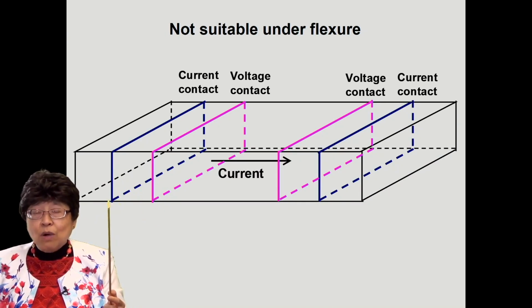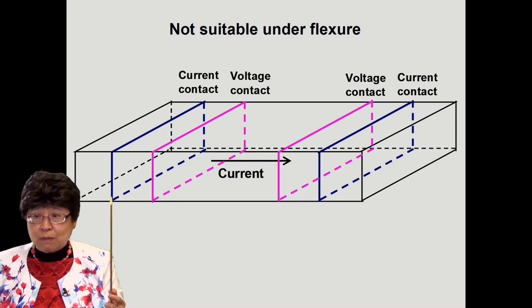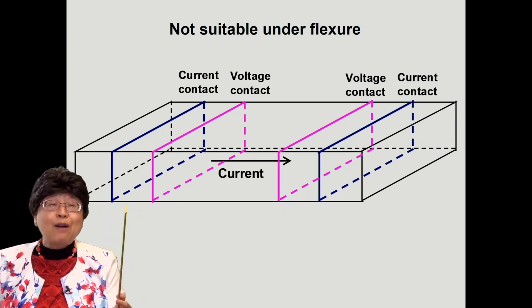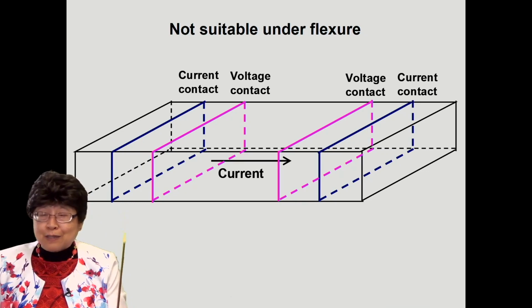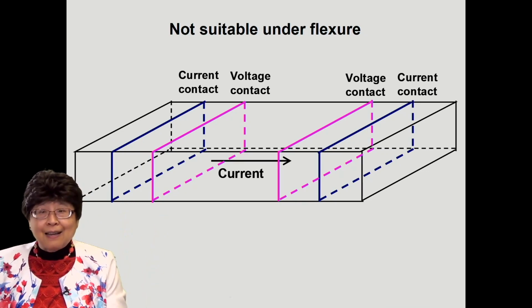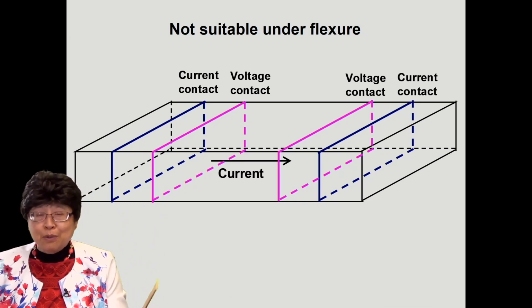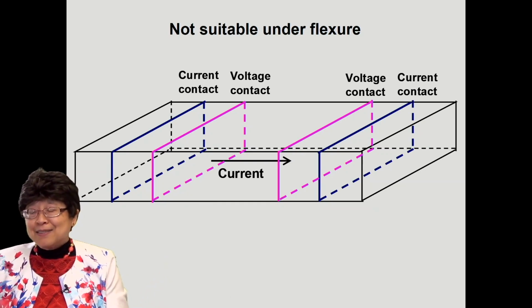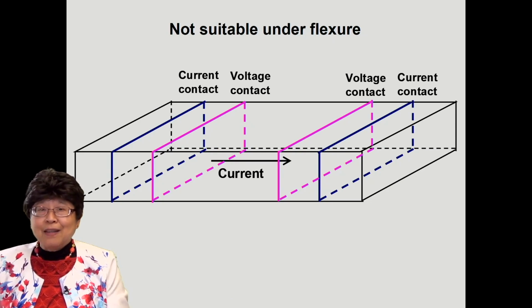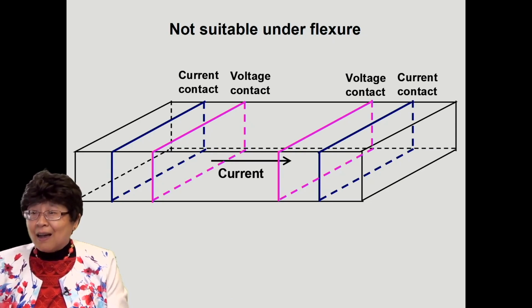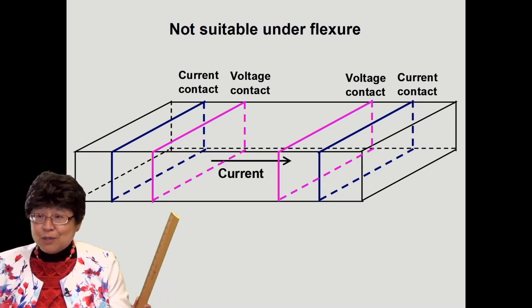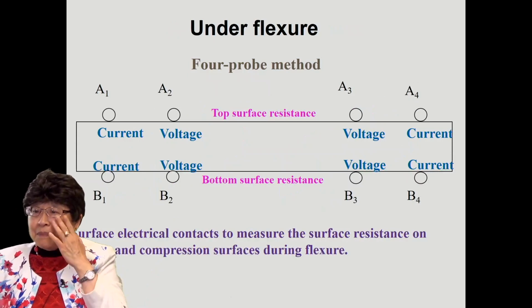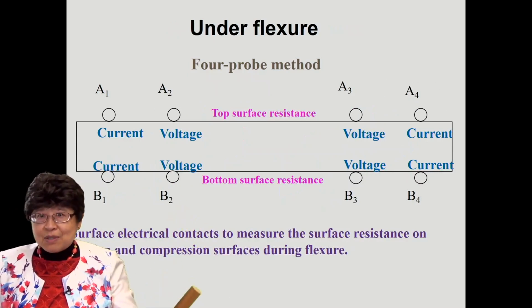Electrode geometry would not be suitable under flexure because you are just averaging out the effects of the two opposite surfaces which behave differently. You're just averaging out the two oppositely behaving surfaces, and so one would get very little effect. The sensitivity would be very small. And some papers have been published using this method. So it's very important to use the right electrical method.